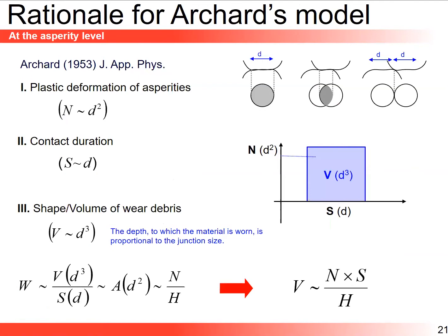Just to tell you where this equation comes from, I told you we'll do this early in my talk. I'm here going back to the classic Archard paper of 1953. Okay? It's a very short paper, beautiful mechanistic insight. So we're looking down at an asperity, at a contact junction here, and we slide it. And as we slide, we lose the contact after a sliding distance of D. We have lost the contact. Okay? And the wear rate, W, is really the ratio of the volume of the debris you form over the sliding distance. I've told you that the sliding distance is proportional to D, and the volume of the debris is proportional to D cubed. So you get a D cubed over D. That's a D squared. D squared is an area. And in Archard's model, the area is proportional to normal load over the hardness. Okay, so V over S equals N over H, therefore V is N times S over H.